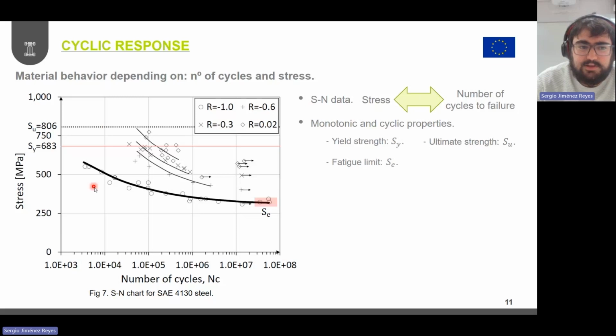And this can be seen through this S-N information, or Wöhler curve information, that relates the stress being applied on a sample and the number of cycles that it takes to fail that sample. Of course, from this type of chart, we can retrieve monotonic and cyclic properties for that specific material. So we can plot here also the yield strength of the material.